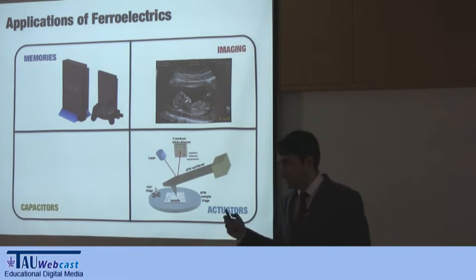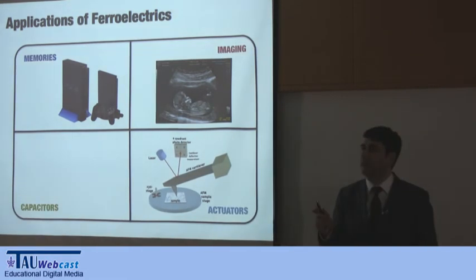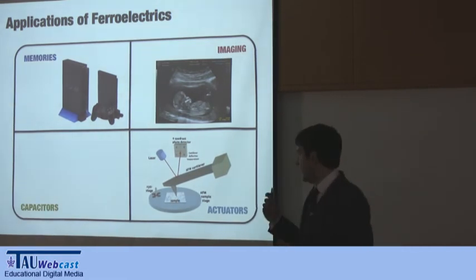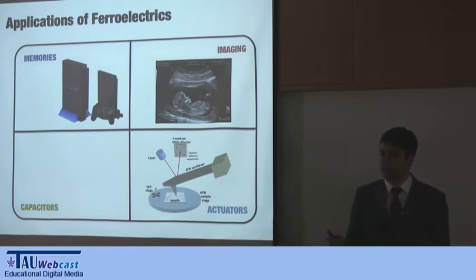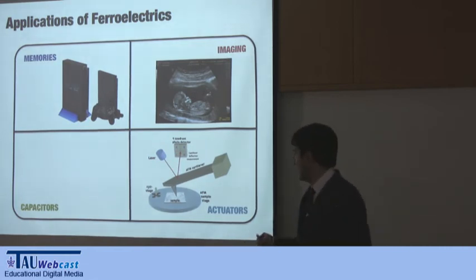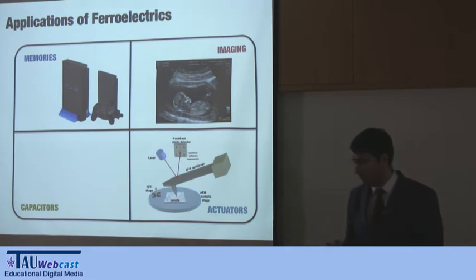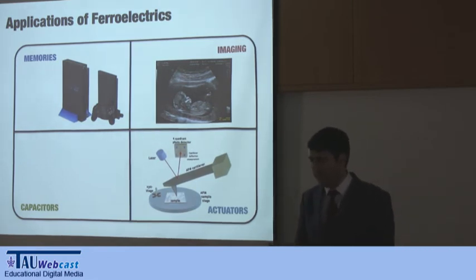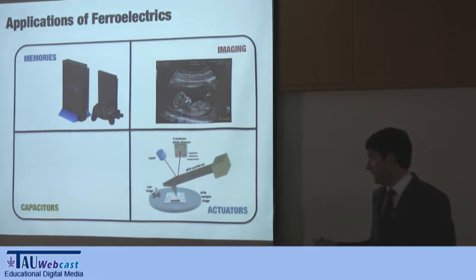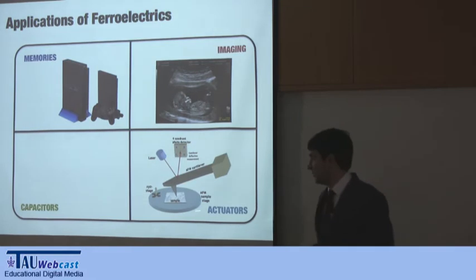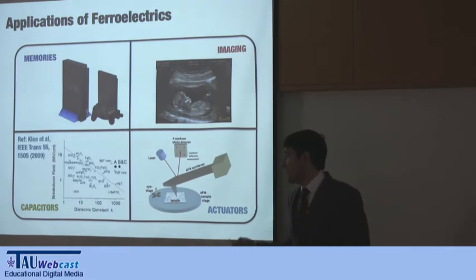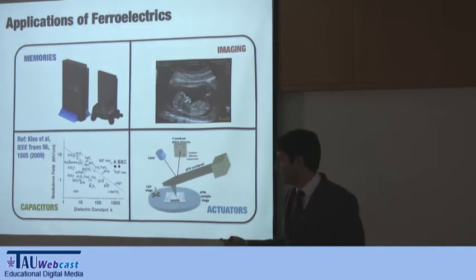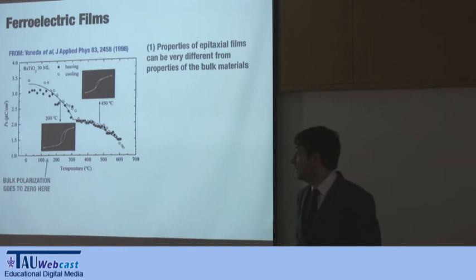The same effect is used when you need to control very little movements of a mechanical device. You can also do this by using the piezoelectric effect. You can move very little a mechanical device with a voltage. An example is an AFM tip. And they are always used in capacitors because they have a very good ratio between the dielectric constant and the breakdown field.